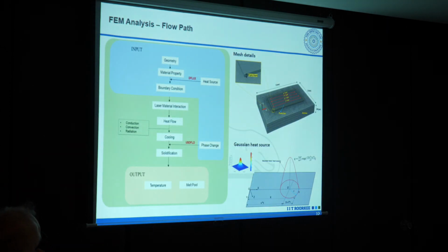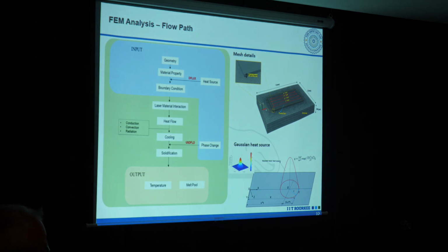Now coming to the analysis part, the FEM analysis part. So this is the full flow part. We basically selected one substrate of steel and printed IN718 on it, and we used the material properties that we obtained from experiments, and a few material properties we selected from the literature. Those are temperature dependent, I'll explain later. Then we used the DFLUX subroutine to model the Gaussian heat source, and again, to see the phase change effect, we have used a user defined field.